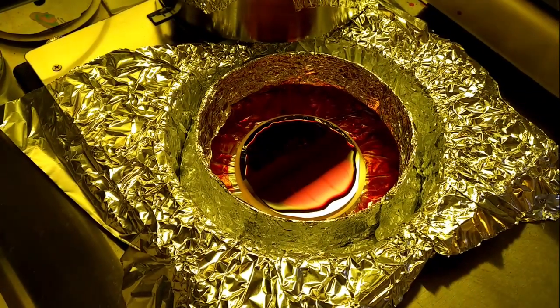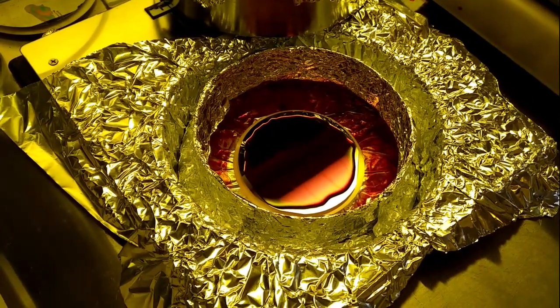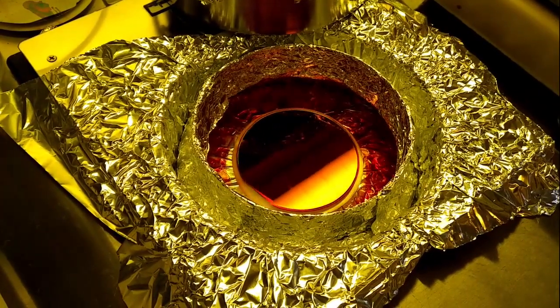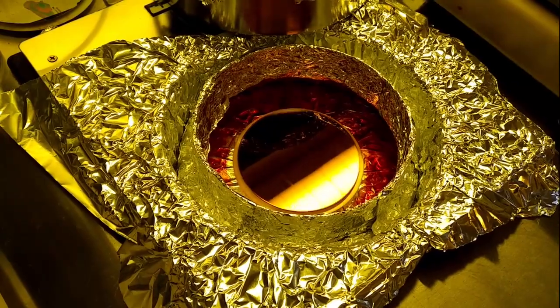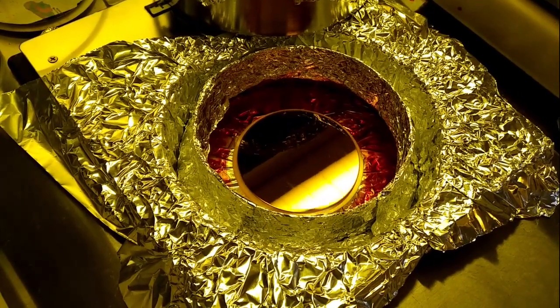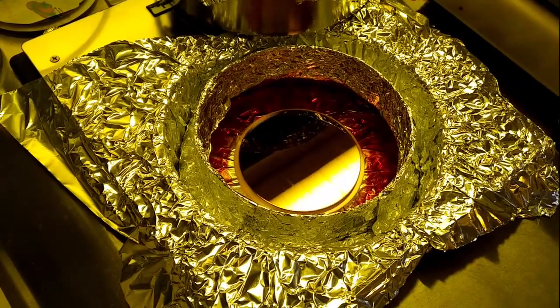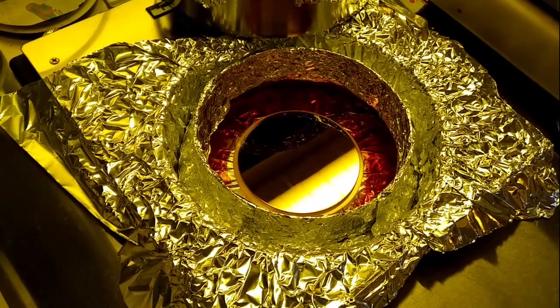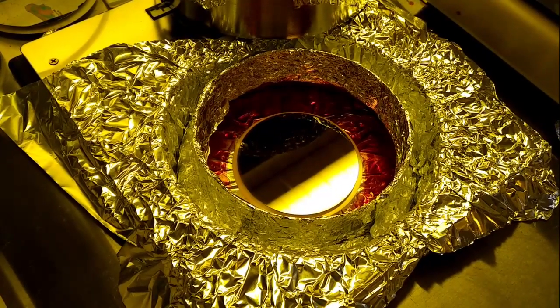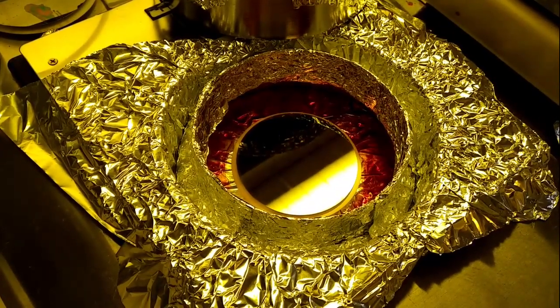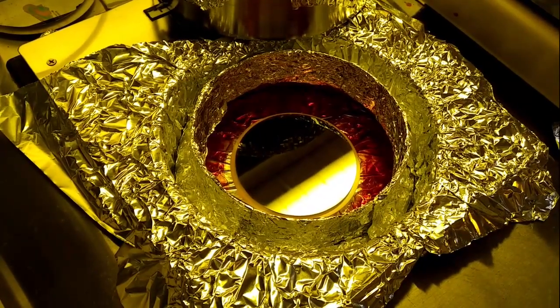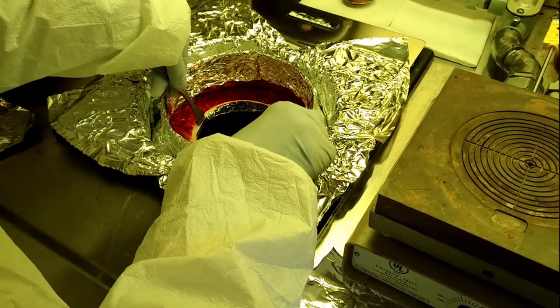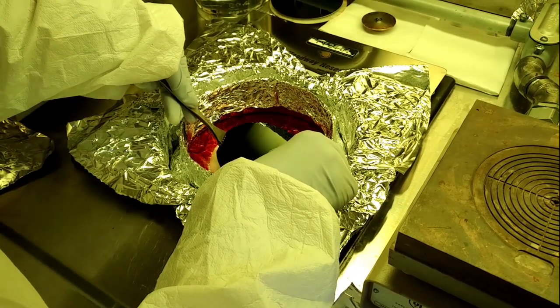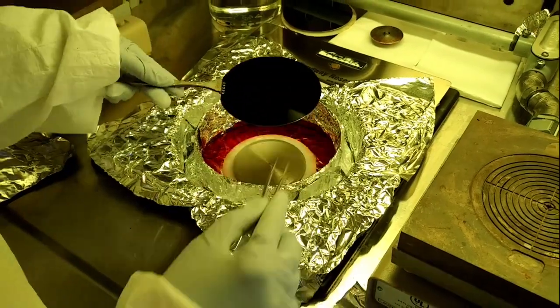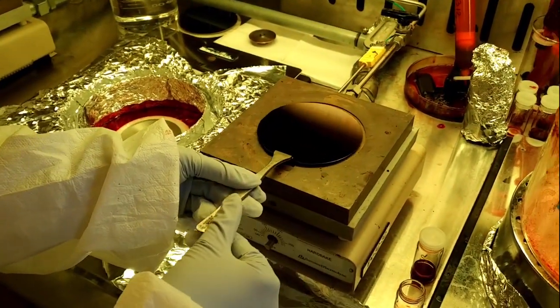The spinner is turned on and the photoresist is shed from the wafer as it spins at 500 RPM for about 10 seconds. Then, the wafer is spun up to 5000 RPM for another 60 seconds to ensure that a thin, uniform coat of photoresist is left on the surface. The wafer is then set on a heater to pre-bake at 110 degrees Celsius for 2 minutes with vacuum applied.